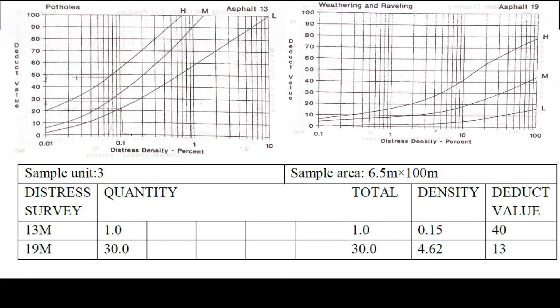To calculate the PCI value, first we add up the total of each severity level. For sample 3, there is a medium pothole and medium raveling, so we got 1.0 and 30.0 respectively. By dividing the total value by the sample area, which is 650 meters square, and times 100, we got the density, which is 0.15 and 4.62 respectively. So we obtain the deduct value according to the respective graph.